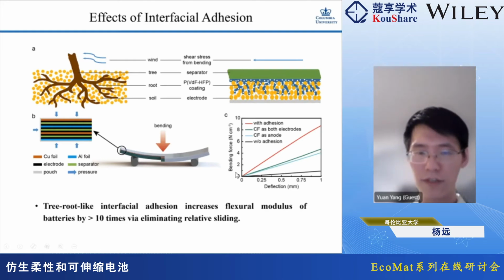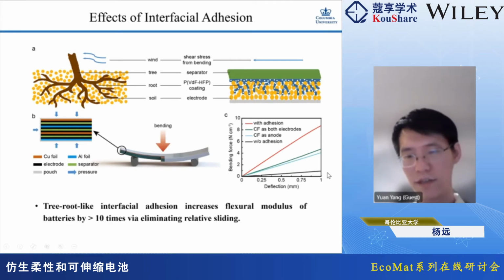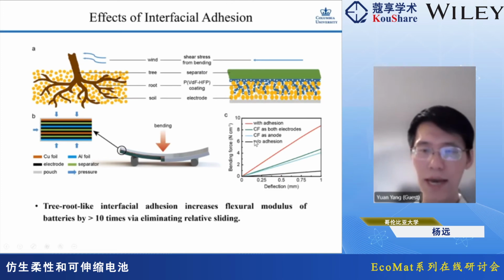To demonstrate this process is valid, we first ran some simulation to show the improvement in the bending force against the deflection of the cell. The slope of this line is proportional to the flexural modulus. Without any adhesion, in a conventional cell, the bending force is very low, which means the modulus of the battery is low. If we use carbon fabric, a common method to enhance the property of structural batteries, even if we use them as two electrodes, the bending force is only increased by 4 times, so it's still not very strong. But if we just have interfacial adhesion between different layers, the bending force can be enhanced by 10 times, one order of magnitude. That's a pretty high improvement.